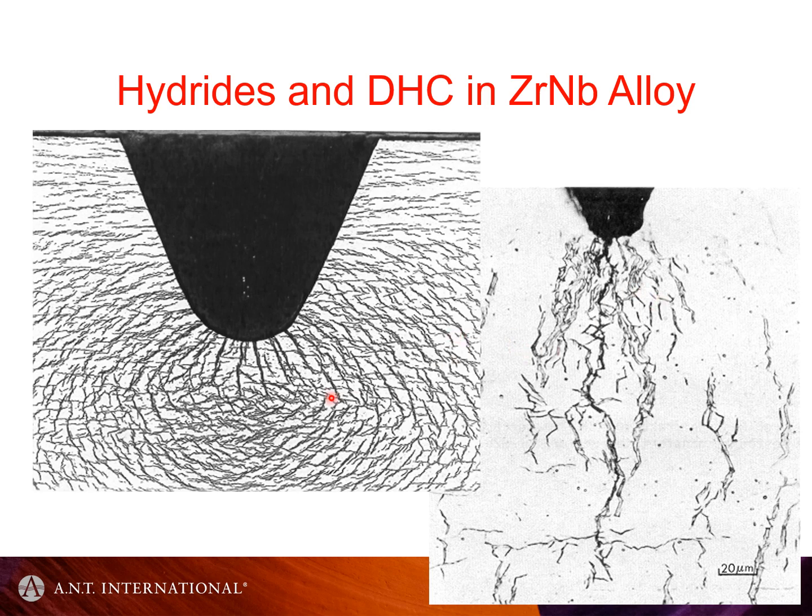So when you have a lot of hydrides forming at a crack tip, in this case it's a blunt notch, but it's still sufficiently high stress to nucleate the hydrides. When you have enough hydrides at the blunt notch, they will crack, as we see here. And what I should have done is shown that this would be subject to some tensile stress in this plane.